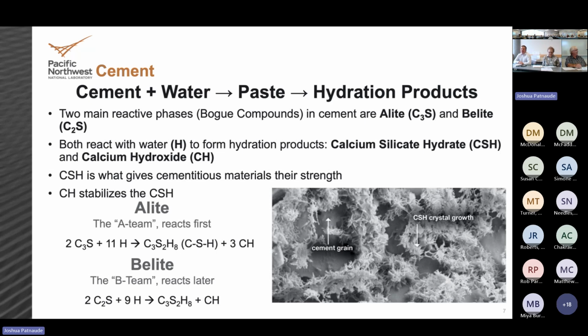But the alite's what reacts first, and then the belite, the dicalcium silicate, the C2S, that's what reacts slower. So after a couple hours, the belite starts to come in, and that's what gives the material its kind of late in life strength. So a lot of the heat that's generated comes from dissolution of the alite, rapid reaction, and the belite reacts second, and that's when the material really starts to solidify. What you end up with are the CSH, which can also be CASH, calcium aluminosilicate hydrates, and then they can also be calcium, sodium, aluminosilicate hydrates, depending on the network and what level of detail you're going into. So that's the main network former.